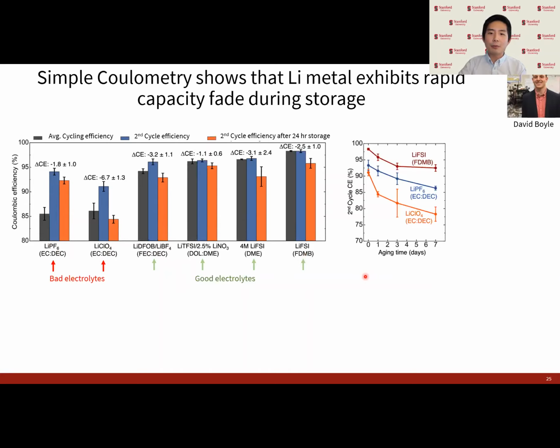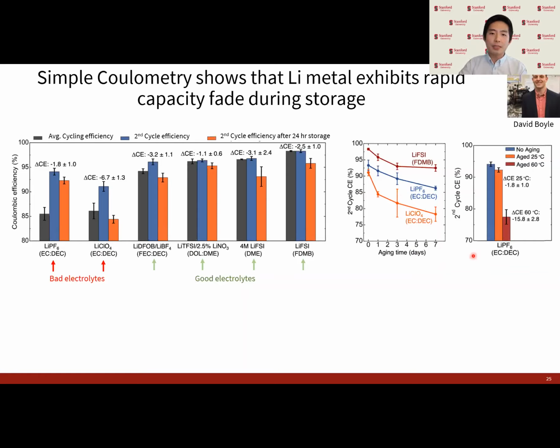If we extend the storage time out to a week, the capacity loss compounds, with the initial 2% loss in the PF6 chemistry and the FSI in FDMB chemistry turning into 6%, and the initial 6% in this lithium perchlorate chemistry further compounding into 15% loss. And by further increasing the temperature, the storage loss gets even worse. At 60 C, this PF6 in carbonate drops from the relatively good value of 1.8% down to 15.8%. And just for reference, what we're seeing is 2 to 7% storage losses in 24 hours. But a good lithium ion battery, even stored at 40 C, will only lose 2% capacity in a year. So even the most stable electrolytes, such as this one, are overall very terrible.